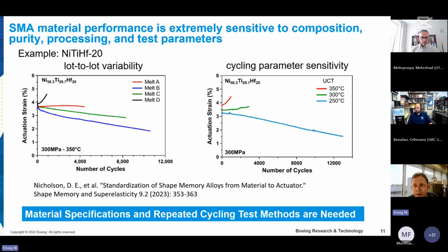We were targeting the exact same processing parameters and composition. If we look to the plot on the right, we can see here now we've taken 1 melt and we're testing it under 3 different upper cycle temperatures: 350 degrees C, 300 degrees C, and 250 degrees C. And you can see here now that there's a significant influence of the upper cycle temperature on the fatigue life in this material system. So what does that tell us? We need material specifications to control the raw material, and we need test methods to control the testing relevant to actuation as we cycle these materials to life. So these are the next 2 pieces of work that we're focused on.